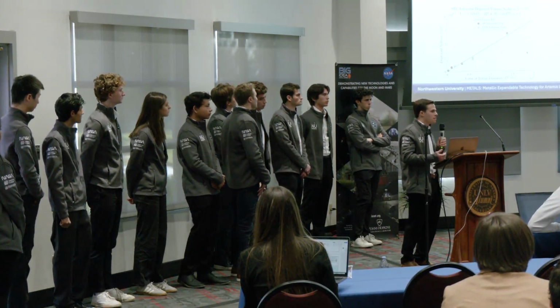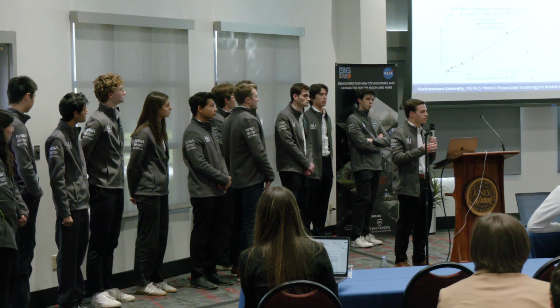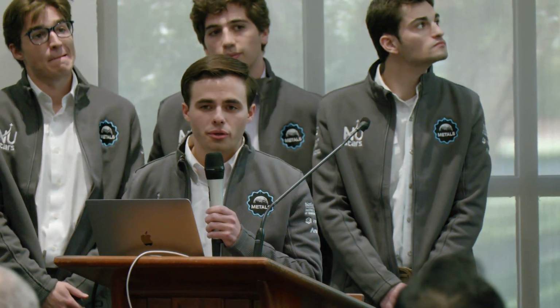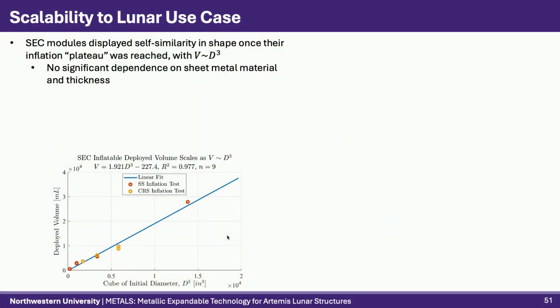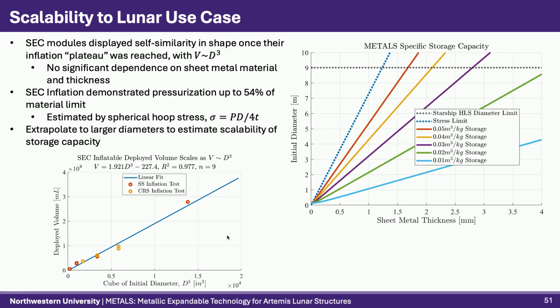During the project, we've demonstrated the scalability of metals from modules of diameter less than 8 inches all the way up to 4 feet in diameter. The true lunar use case will require modules even larger than that, but the path forward for scalability is very promising. First, our experiments showed that the deployed volume of the SEC modules scales as the initial diameter cubed, unsurprisingly, but surprisingly, with no significant dependence on the sheet metal material and thickness, showing how the SEC shape guides the deformation into a self-similar topology regardless of the scale.